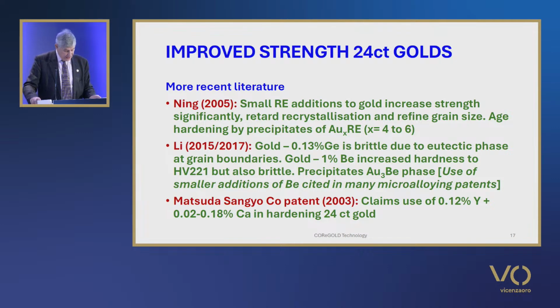In a further study, he reported work on hardening of fine gold by 1% additions of beryllium, and he found that the beryllium addition increased the hardness of gold to about 221 Vickers, but that the alloy was brittle and fractured on attempts to roll it. The as-cast grain size was refined and the microstructure comprised gold dendrites and eutectic phase of gold and the gold-3 beryllium intermetallic. The phase diagram indicates there is almost no solid solubility of beryllium in gold. This work has relevance to microalloying since the use of smaller additions of beryllium are cited in many of the patents.